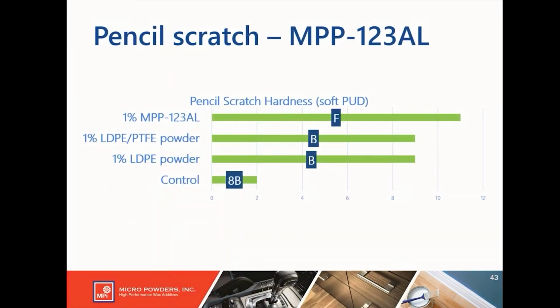Again, soft PUD control is 8B. 1% of LDPE powder improves to a B. In this study, the LDPE PTFE powder has the same result, a B. But MPP-123AL, so that's LDPE alumina, best results with an F pencil scratch hardness rating.